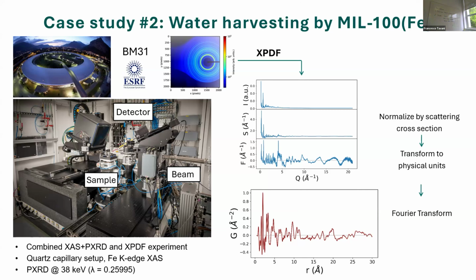In the case of PDF, you collect the diffraction on this large and very expensive 2D detector, which generates a 2D diffraction image, which is then converted to 1D. You apply different post-processing normalizations and transformations, followed by a Fourier transform, and at the end you obtain the PDF. This is what a PDF would look like, and all these peaks are, as I mentioned earlier, related to the persistence of a specific interatomic distance present in your material. For example, you have the carbon-carbon peak, the iron-iron first neighbor peak, and so on.